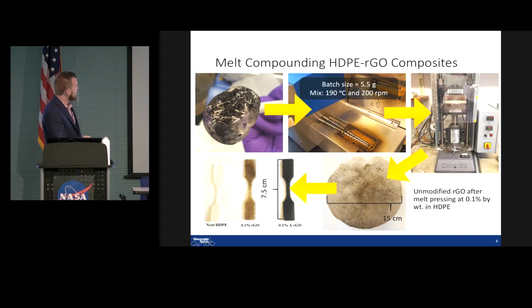So this is the same as this pancake film. And then this is the alkylated version. So these feature the exact same amount of the reduced graphene oxide. One is just chemically modified to be more miscible. The other is unmodified and therefore is much more prone to aggregation.